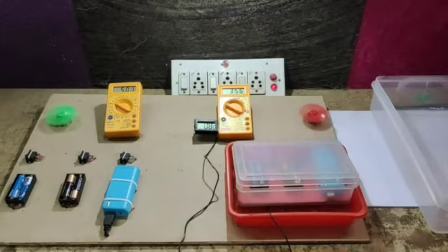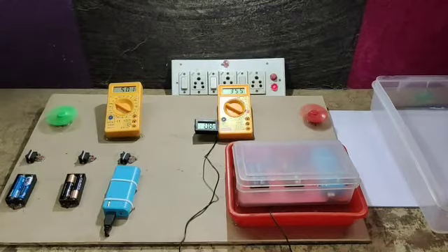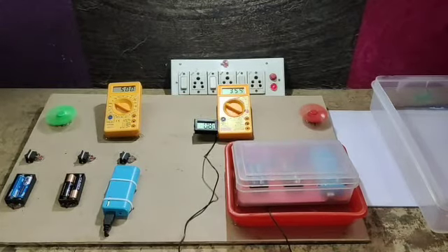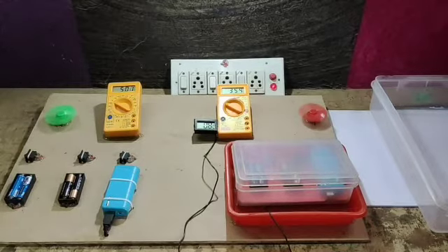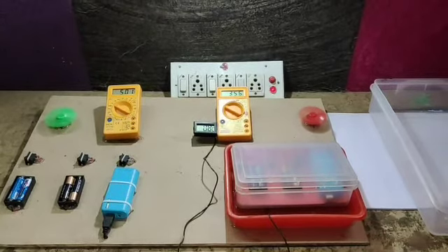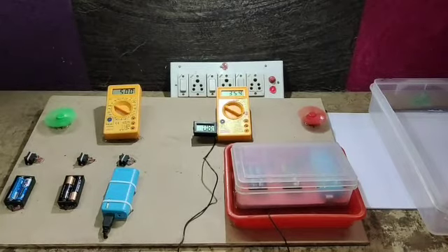And if the temperature goes high, above 60 degrees, there is a chance of explosion. So it is better to use them between 20 and 40 degrees. Lithium polymer batteries work better at 20 to 40 degrees. So here we can decide that lithium batteries work better at 20 to 40 degrees, and we will get around 95% of the output.